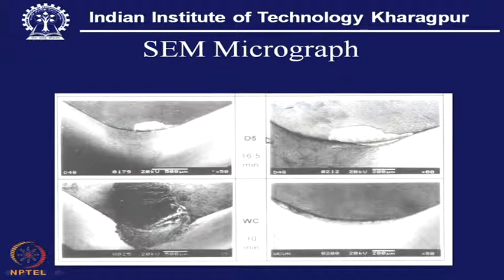Now, here also it is something very interesting. When the tool's top surface is a non-compatible tool, the chip gets stuck. However, when it is a diamond coating, the chip does not stick, but we can also examine how long this coating can survive. Here we can see this is the substrate and that is the coating. There is also a certain limitation on the coating: after doing all the machining, damage is not much on the flank, but the chip is flowing on this side, and because of some weakness at that point of time, the coating got flaked in this area, exposing the substrate. But in this case, this is the principal flank side, with only a little bit of chipping, and on this side the coating is still retained.